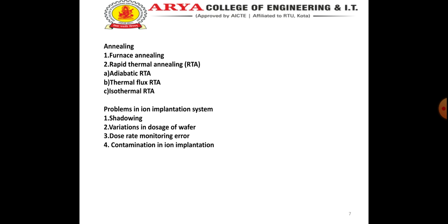Now, contamination in ion implantation. Implanters have four types of commonly seen contamination. One type of contamination is particles. If the particles fall on the wafer before implantation, they will screen the wafer from the implant. A later clean may remove the particle, but its unseen shadow remains behind as a virtually undetectable killing effect. The other three types of contamination are related to much smaller impurities that may fall on the wafer during implantation.